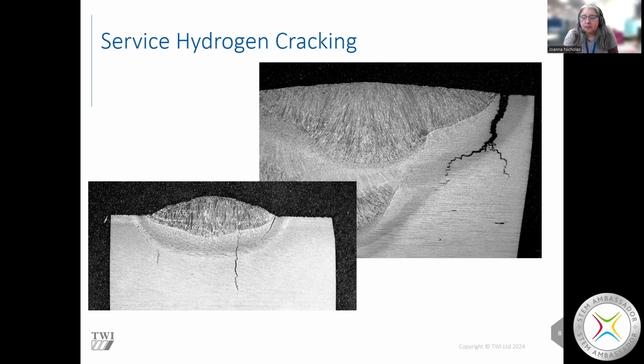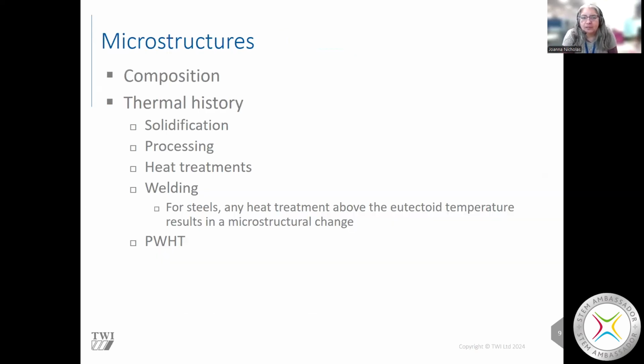So obviously we don't want any cracking in something that we've made, so we do want to try and avoid it by modifying the microstructure. The microstructures are always based on the composition of the steel and then the thermal history. The thermal history comes from the welding process itself, from the solidification of maybe the parent material. What processing has it had? Have there been any heat treatments? Has there been any welding? Because welding is another solidification or heat treatment of the material.